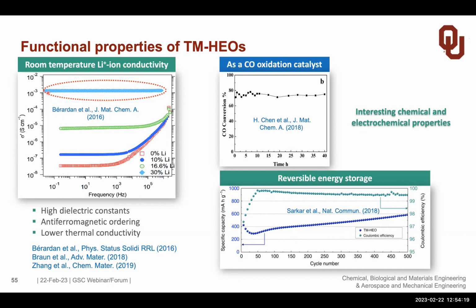And this group has found a very high room temperature lithium-ion conductivity in a material which contains up to 30% of lithium in addition to the 5 transition metals. It has also been used in catalysis, and in our own work, we have used it as cathodes and anodes for lithium-ion batteries, but also for sodium-ion batteries.